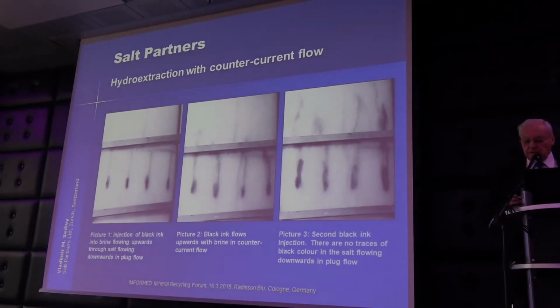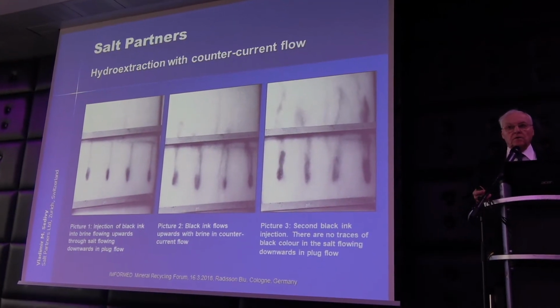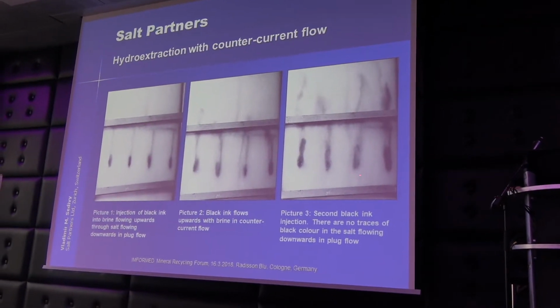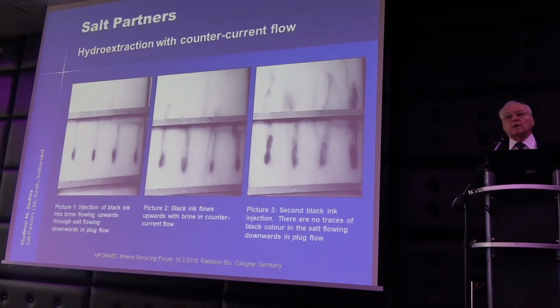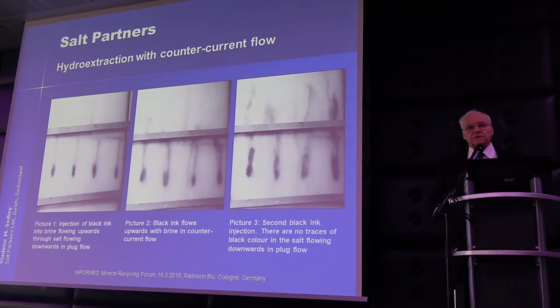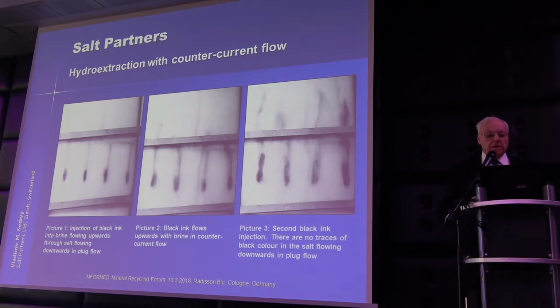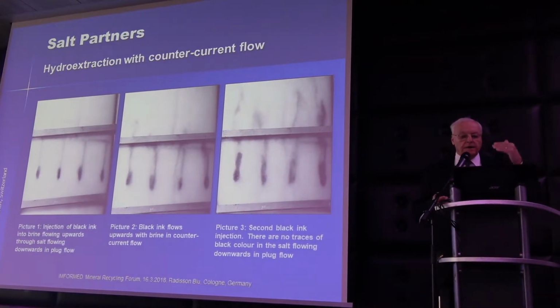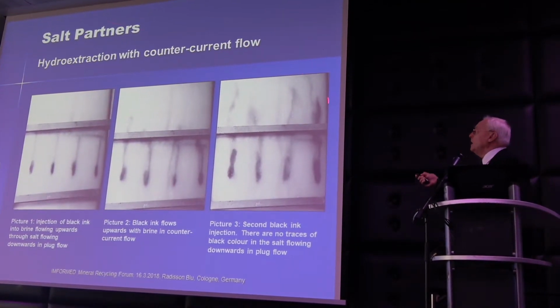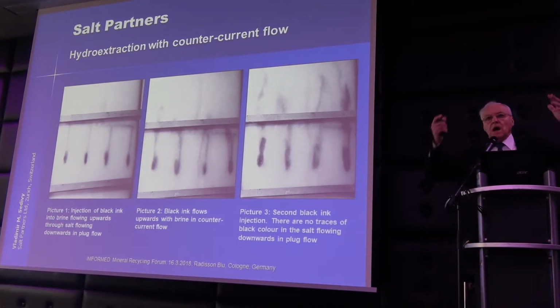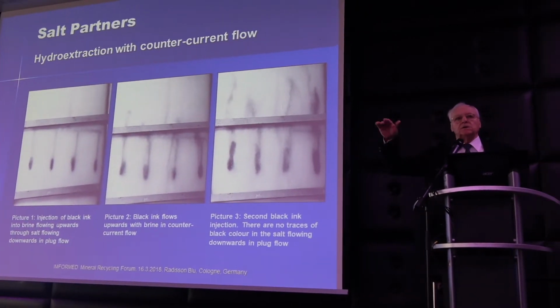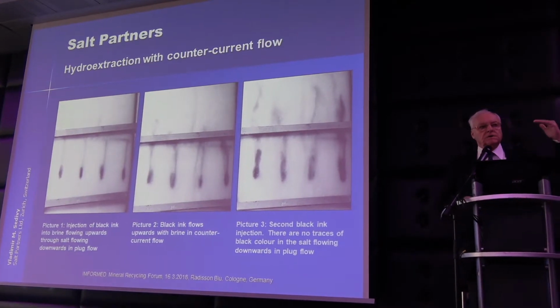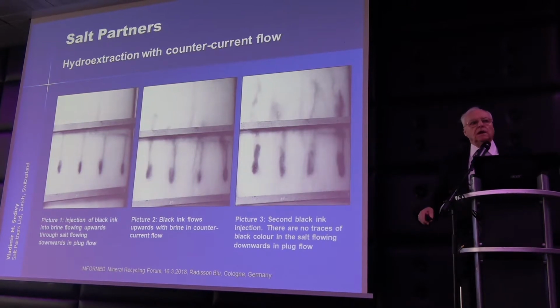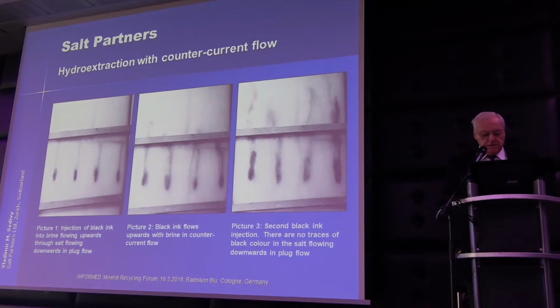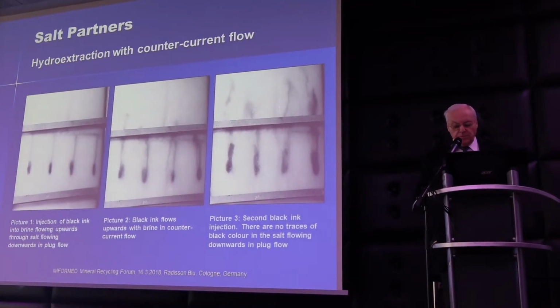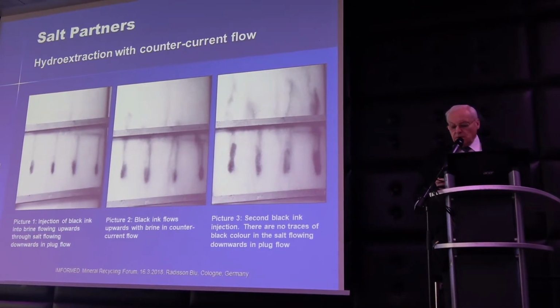So what you can see here is that, first of all, the black brine flows upwards, here and here. Below the injection point of this black brine, you do not see any black brine at all. It is all moved upwards. And then you can see that there is some diffusion of this black brine in the upper section, here. So you need a certain height, a certain elevation. It's like distillation. In a distillation with a packed column, you have theoretical trays, and you need a certain number of these theoretical trays to get the heavy liquid down and the light liquid up. So these are the chemical engineering principles of the process. The most important one. There are others that I am not going to